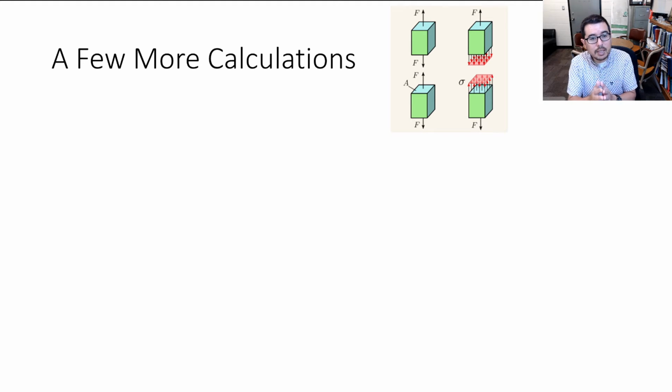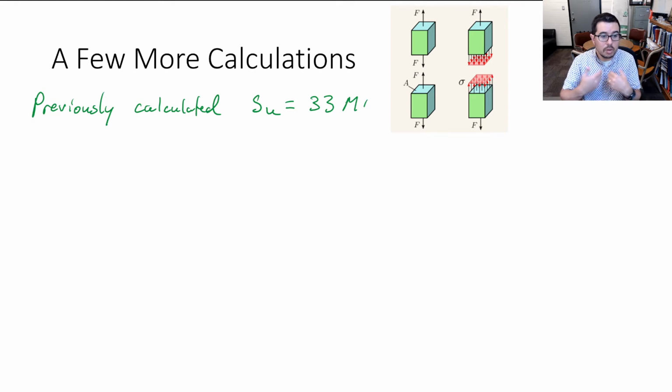As we've discussed in the notes that you've seen on the website, we have the ability to talk about what an ultimate tensile strength might be. So in a previous test in the lab, we took a piece of paper that you're going to be using, and we calculated or estimated an ultimate tensile strength of 33 megapascals. Now, this is not a 100% precise number. There are a number of factors that can go into the uncertainty that guides this number being high or low.